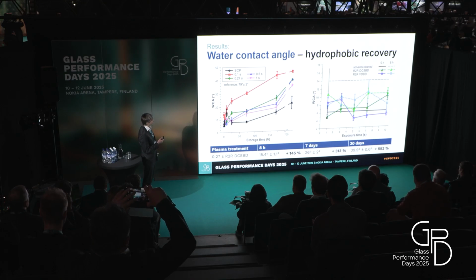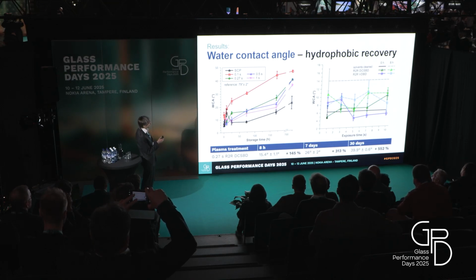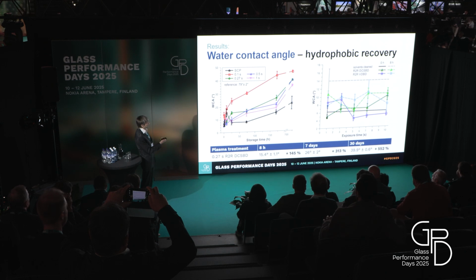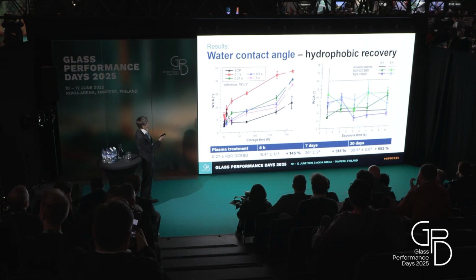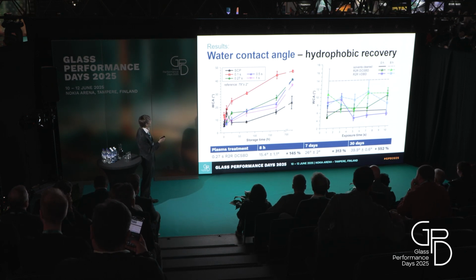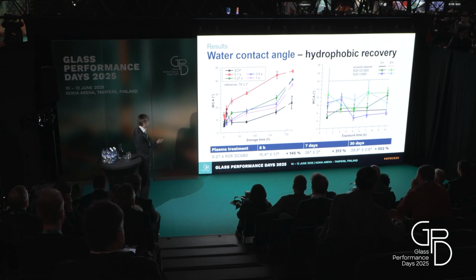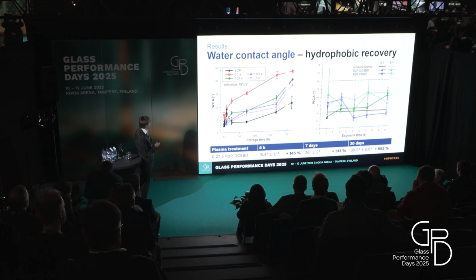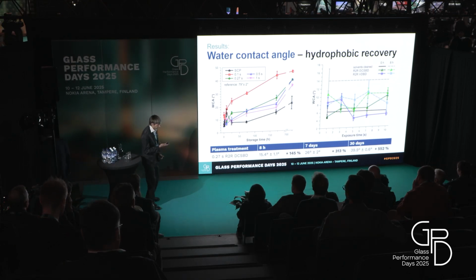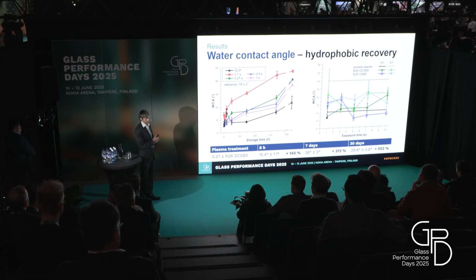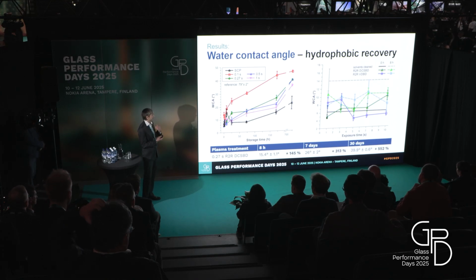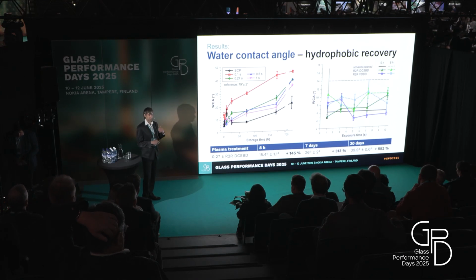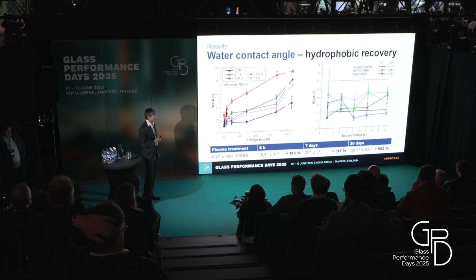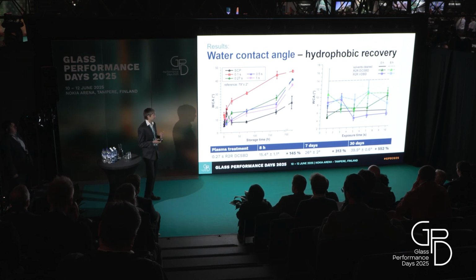But we can see that after the first 8 hours, it's not recovered so much. It's still around 10 degrees or below. But after then, maybe it's still rising. So you can see that for inline implementation, this cannot be a problem. But why am I showing you this? Because we can see the difference between the exposure time and between the effects of plasma. And this is because there are more processes which are contributing to this effect.